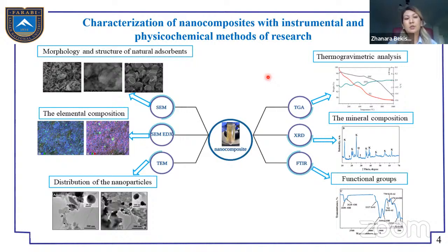The characterization of nanocomposites was done by instrumental physical-chemical research methods. The morphology and structure of natural adsorbents was studied by scanning electron microscopy, and the elemental composition of natural adsorbents and composites with silver nanoparticles and silver chloride was studied by SEM-EDX spectral analysis. The changes of temperature and physicochemical changes were studied by thermogravimetric analysis, and the mineral composition and formation of silver and silver chloride nanoparticles by X-ray diffraction, functional groups by FTIR spectroscopy, and distribution, size, and shape of nanoparticles by transmission electron microscopy.